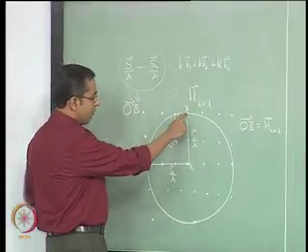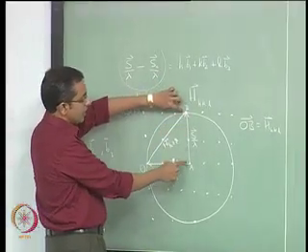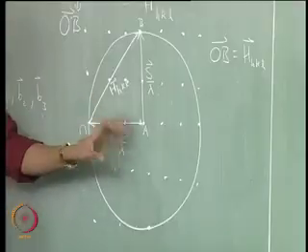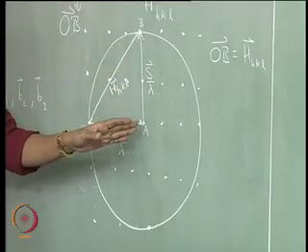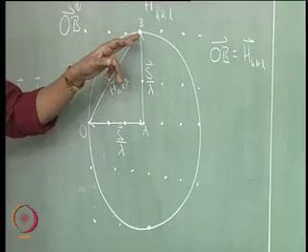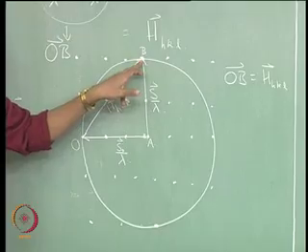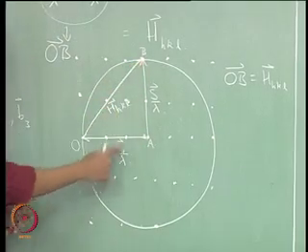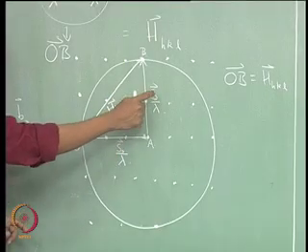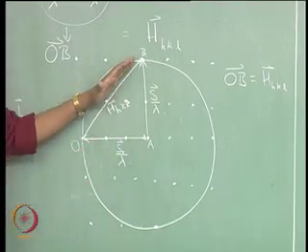And at those particular locations you can now define that wave vector s by lambda, so at that point you not only have the correct magnitude, which is 1 by lambda, but you also have a direction such that the difference between the incident beam vector and the diffracted beam vector is a valid reciprocal lattice vector.